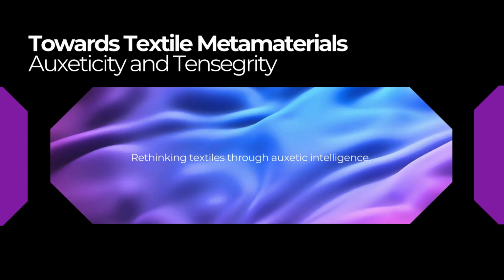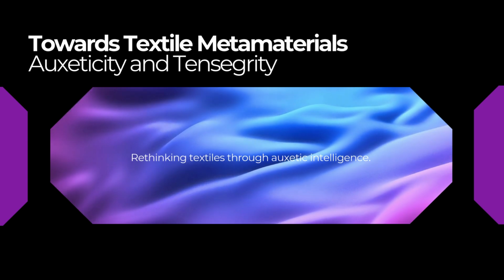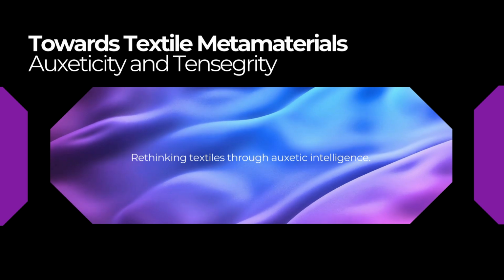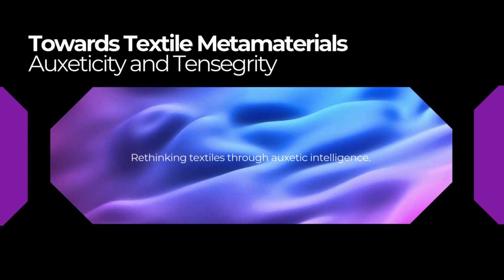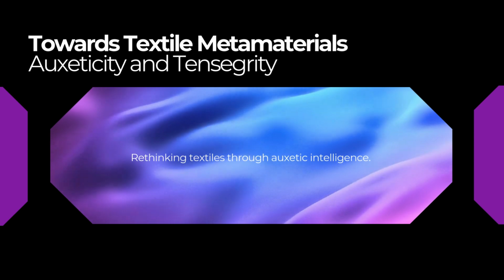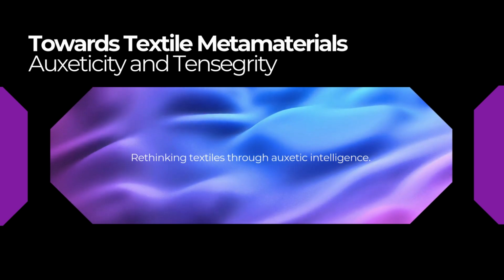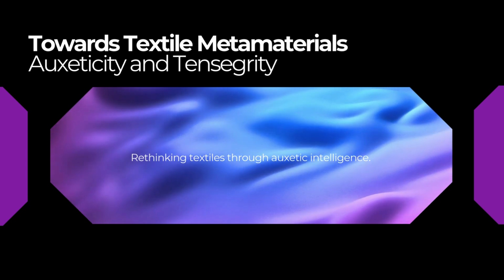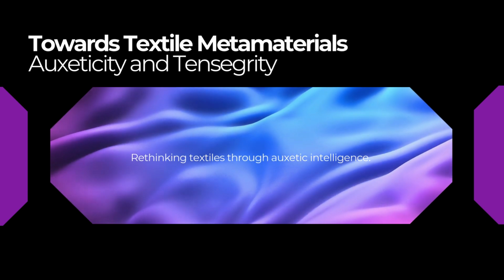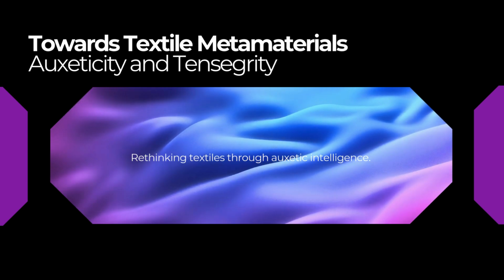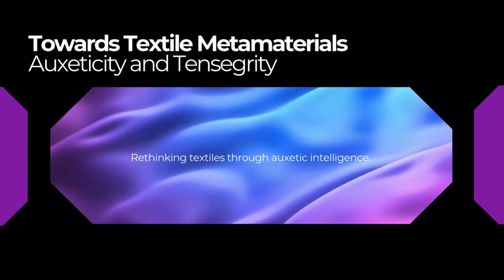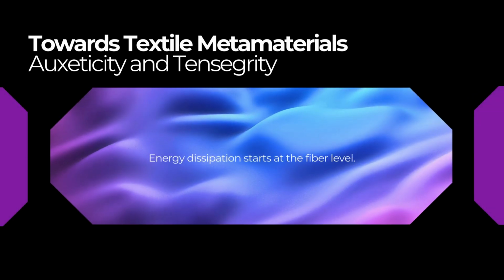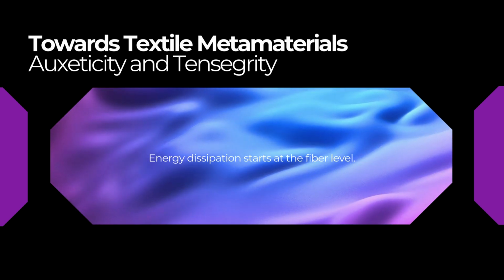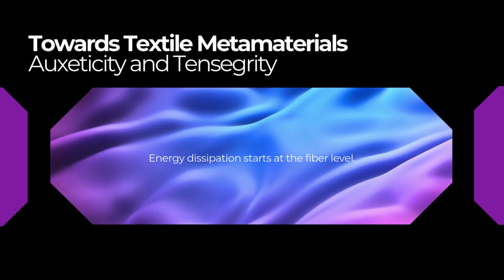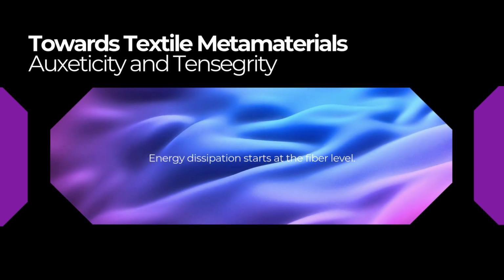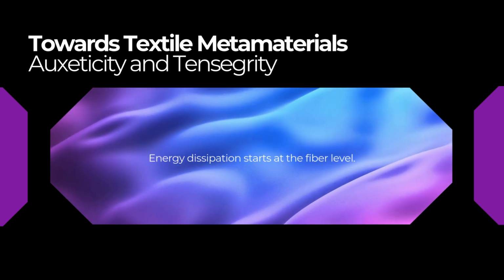At high strains, you are breaking delicate interfiber bonds or permanently changing the geometry of the entanglements and those buckled columns. This explains why the material's reversibility dropped off after multiple pulls. It was finding a new, softer configuration with each destructive cycle. This whole discussion of stability, elasticity, controlled failure, and this push-pull between entanglement and fused bonds, it all leads to the conceptual aha moment of this research. The connection between the behavior of this simple stiff felt, and the advanced engineering concept of tensegrity.